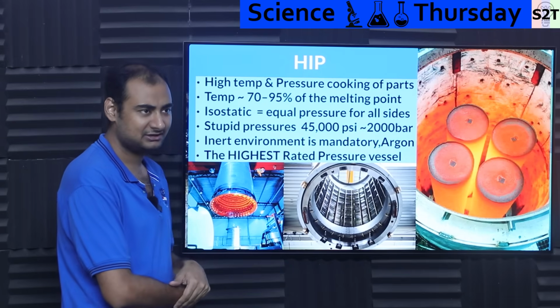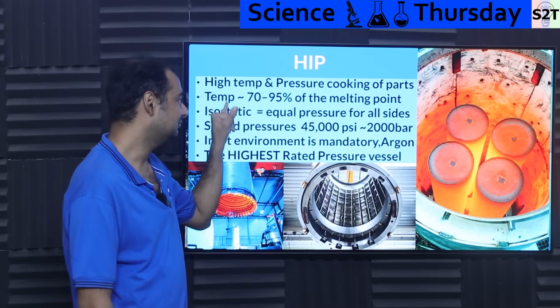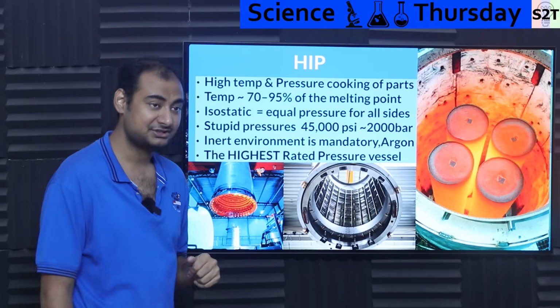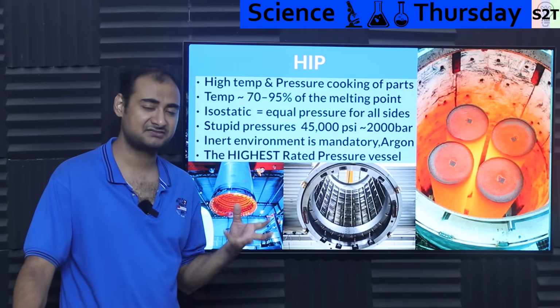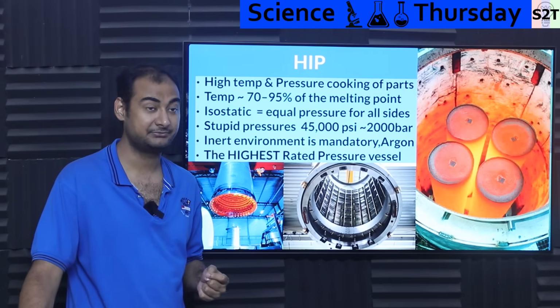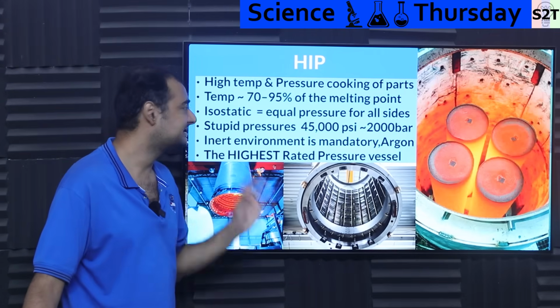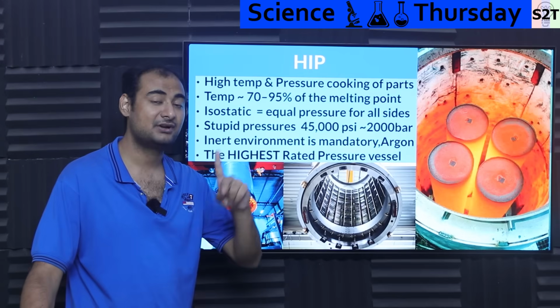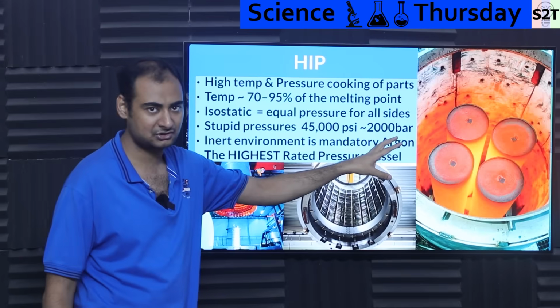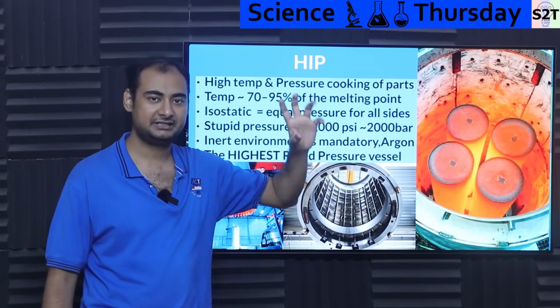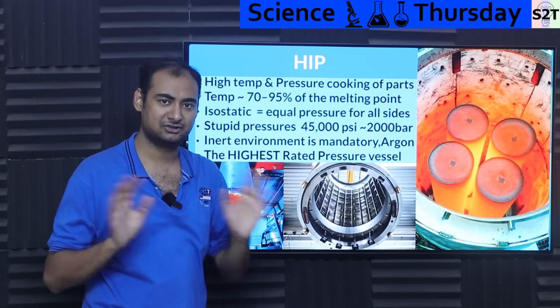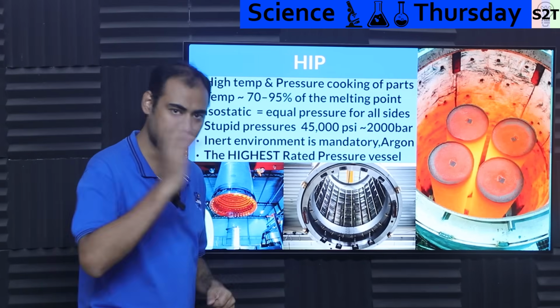Generally, depending on the alloys and the mixture and composition, you will be at 70% of its melting temperature or 95%. Some alloys, specifically ceramics, do require that kind of high temperature. But most of the time, you will be at 70 to 95% of the melting temperature. You do not want it to melt, meaning once you send structures into it, it's a fully formed structure. You're not supposed to say, oh, I did it and now I'm going to do machining and grinding. No, this is supposed to be the last step. You put it there, you use it, done.